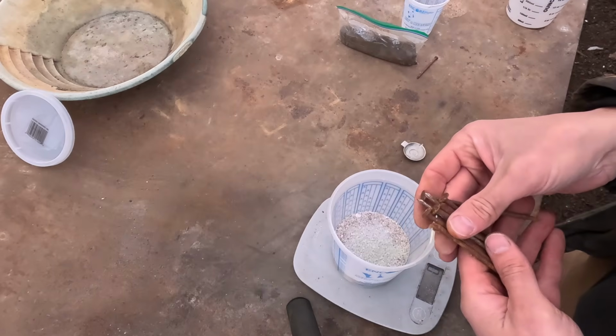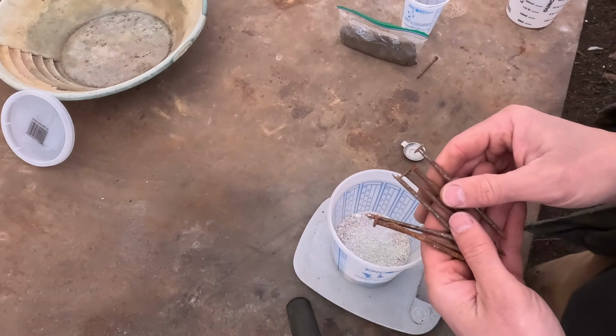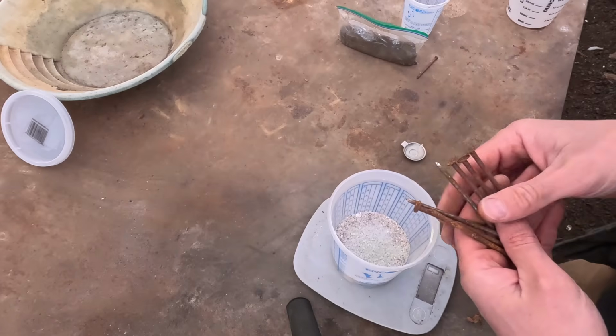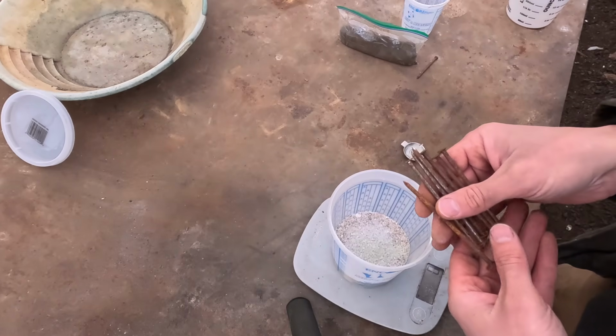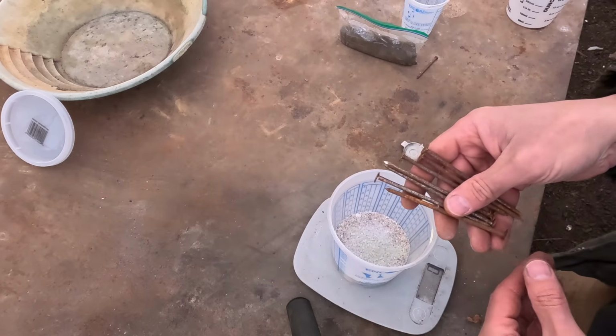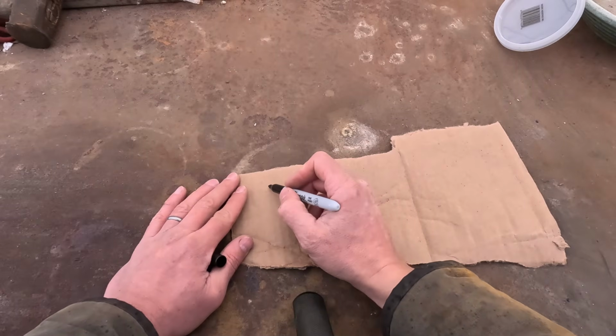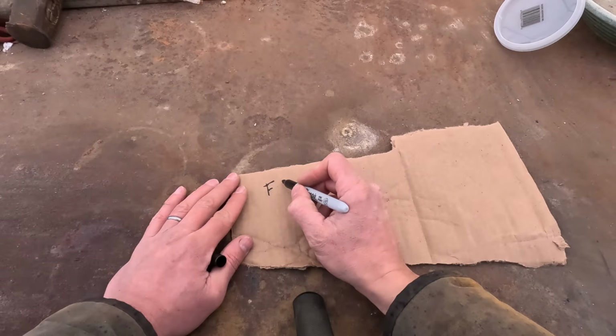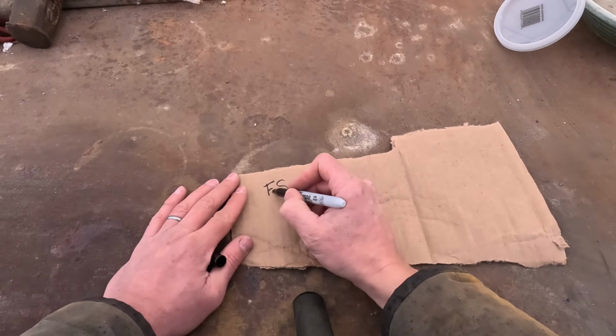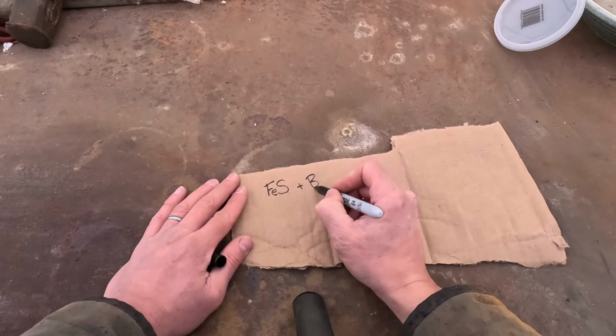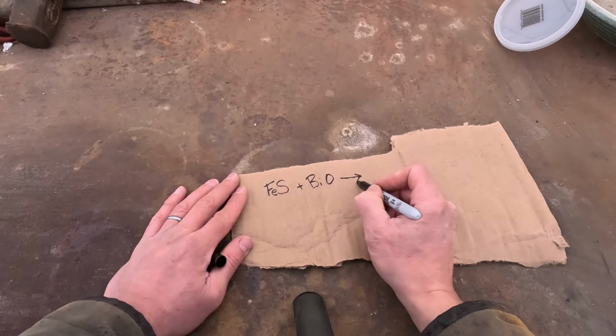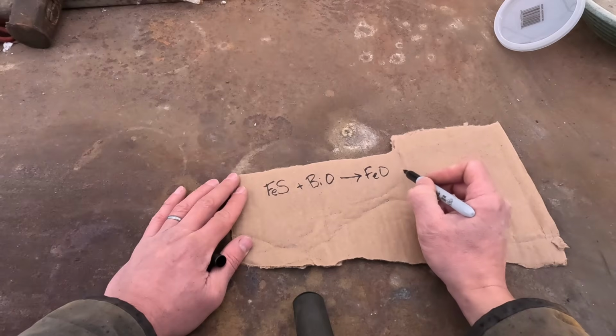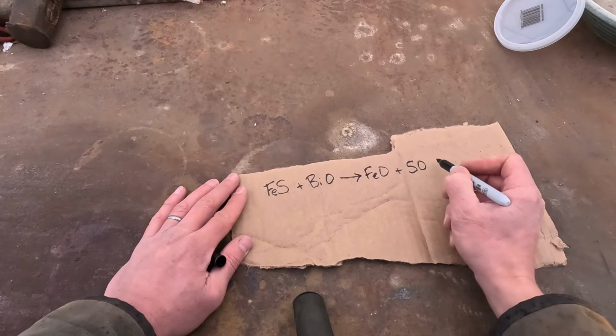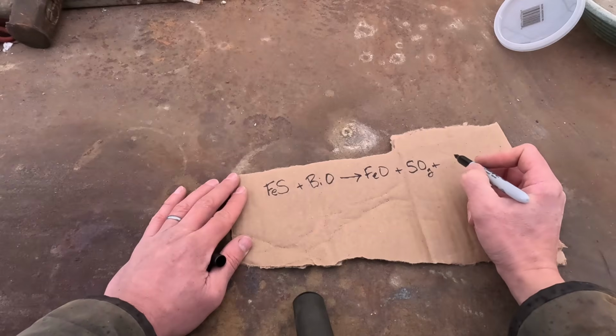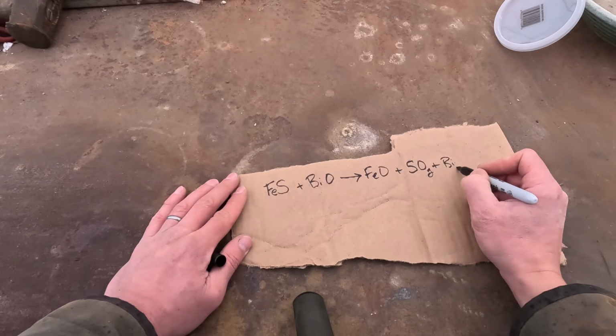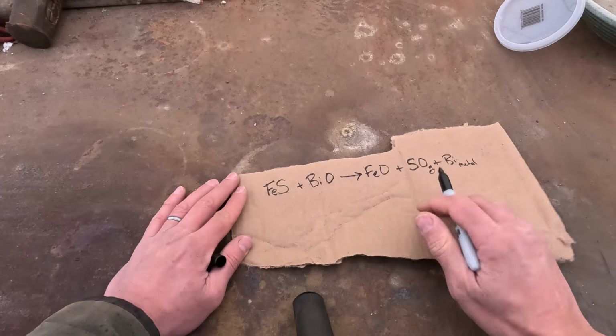And this gets a little bit complicated, but it essentially acts just like the oxygen does in our oxidizers that we put in. But let me write out the chemistry on a piece of paper so you get an idea of what the iron nails do. Right off the bat, I'm going to piss a bunch of people off because I'm not going to balance these. But let's say we have an iron sulfide, FeS, and it reacts with a bismuth oxide. You end up with iron oxide plus sulfur oxide as a gas plus bismuth metal. Okay, so that's how the oxidation part works.